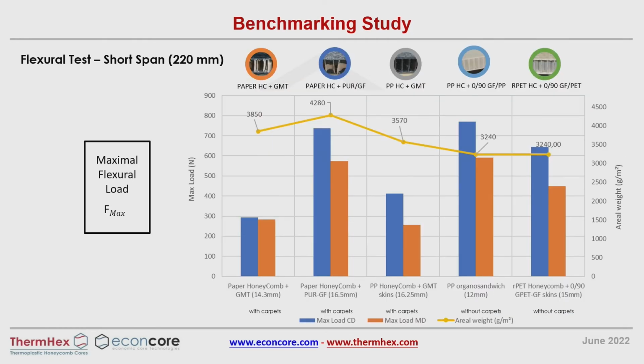If you look at the different performance, this is the 3-point bending load. You see the first one was the part which they had to replace, the polyurethane part with paper honeycomb and glass fiber, but this was not moisture resistant enough. Because if you have the paper honeycomb not impregnated with the polyurethane, then it's not moisture resistant, and they had problems with this. So our target was column number 3, to replace the first column with a thermoplastic honeycomb and glass fiber mats.